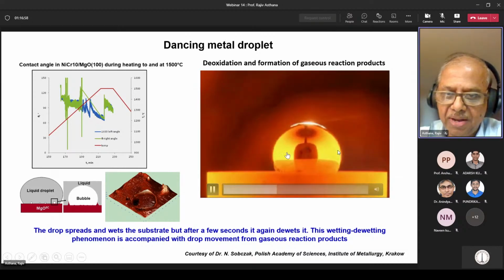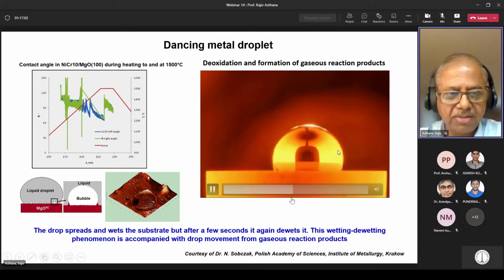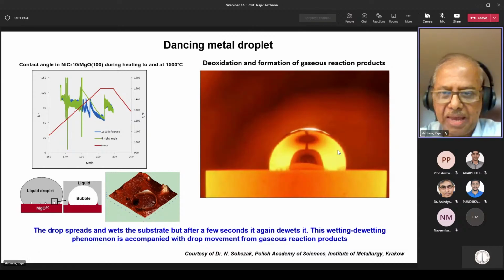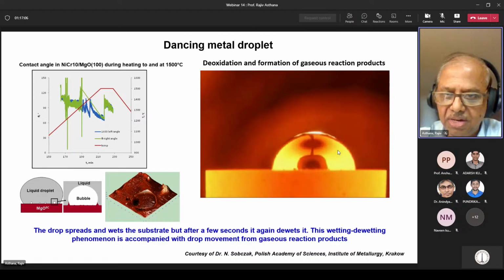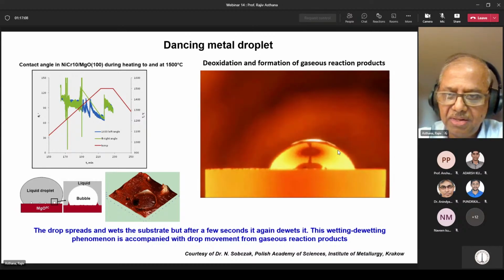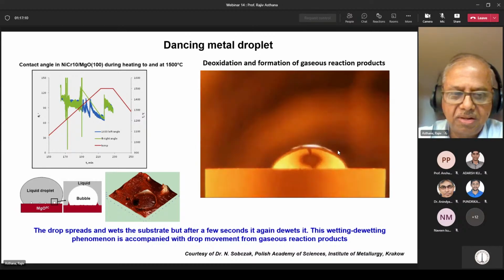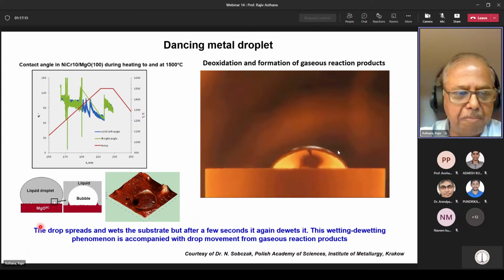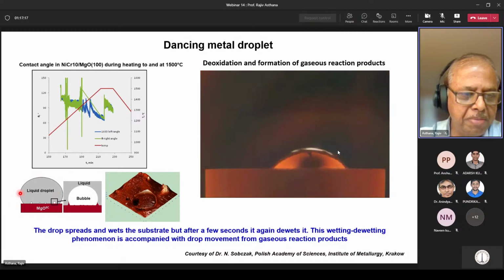If you go back and look at this area, this is during the heating process, and we are looking at very long times, 200 minutes, 230 minutes of contact time. So this kind of a process takes place mainly because under this 2 millimeter droplet, you have these teeny gas bubbles that evolve either from reaction or from degassing of the substrate, and they cause the droplet to dance around.